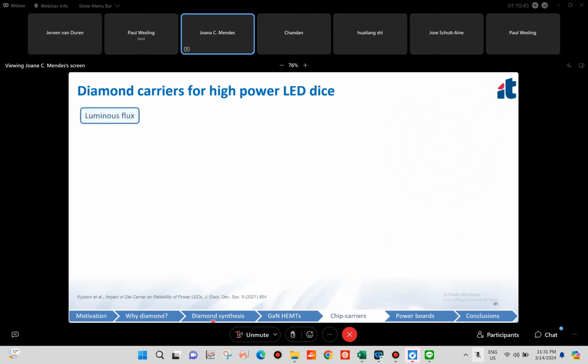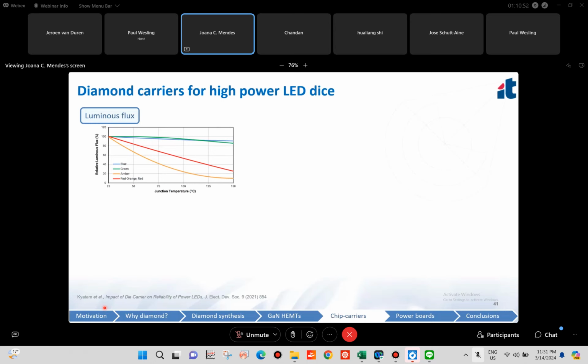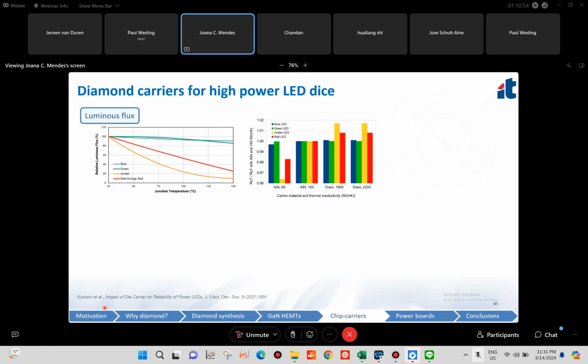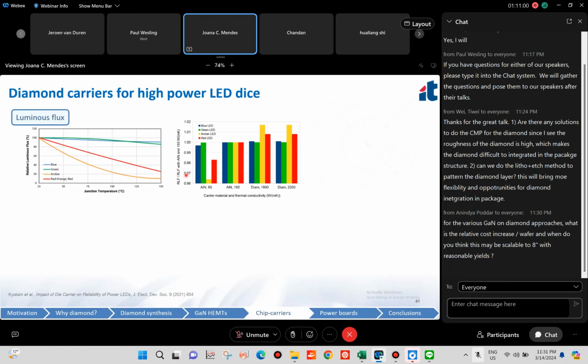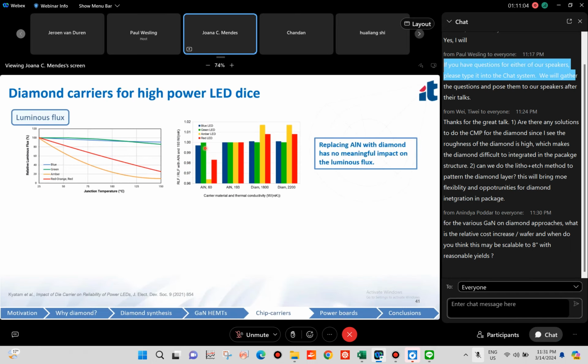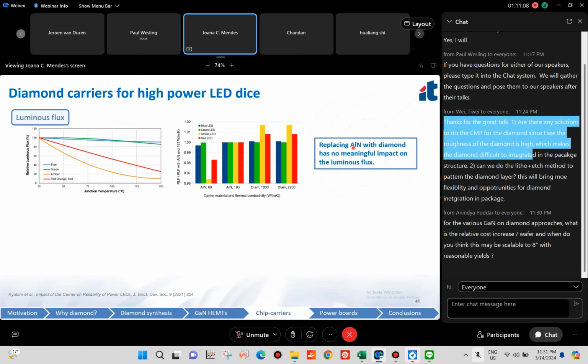So we proceeded to evaluate the impact of the diamond carriers on the luminous flux. So we took a look at the datasheet of the devices, and we calculated for the different types of LEDs, blue, green, amber, and red, what would happen to the relative luminous flux, and we saw that there's really not much difference. So replacing AlN with diamond doesn't bring any advantage in terms of luminous flux.